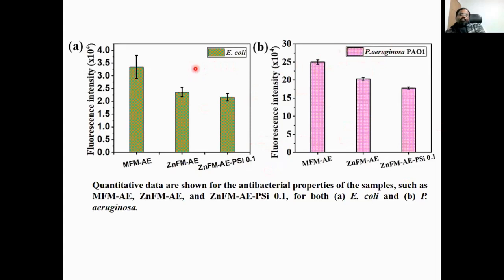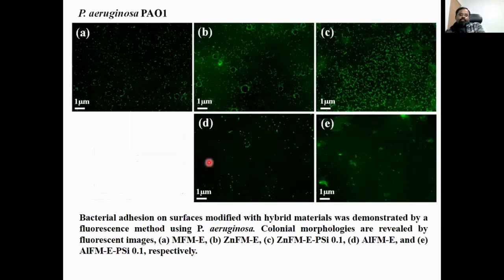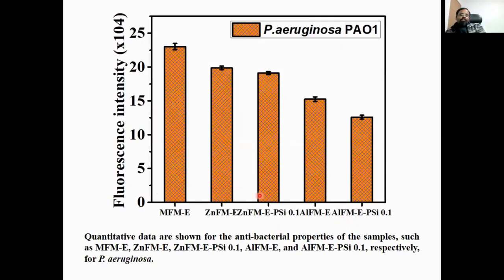Compared with Pseudomonas, the effect on E. coli bacteria is quite good for these coated materials. Further, we compared Pseudomonas bacteria with the aluminum source, and compared with zinc, aluminum shows much better results for Pseudomonas bacteria. So the antibacterial properties can differ based on the bacteria, the surface coating, and the metal source.